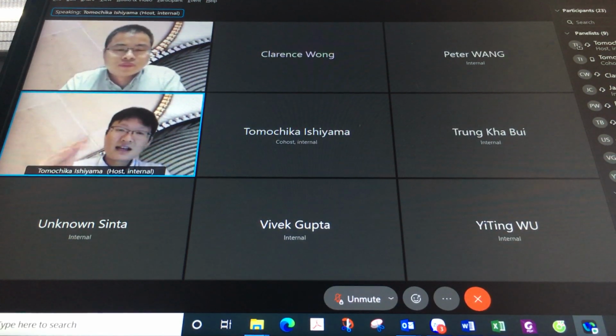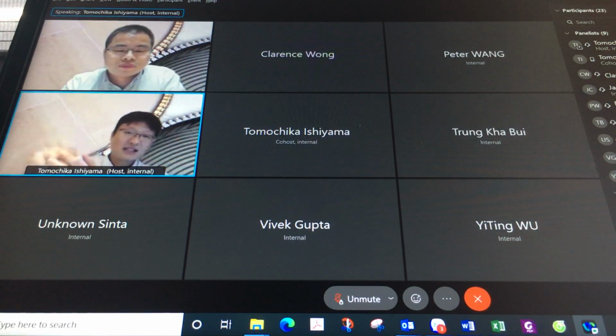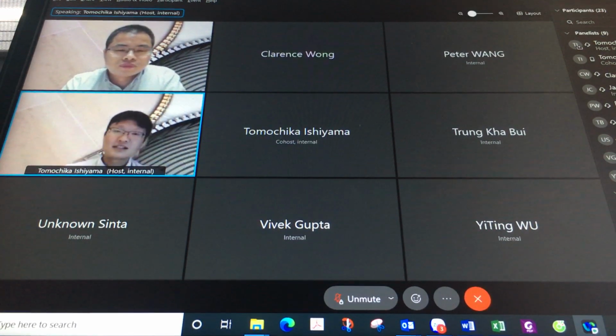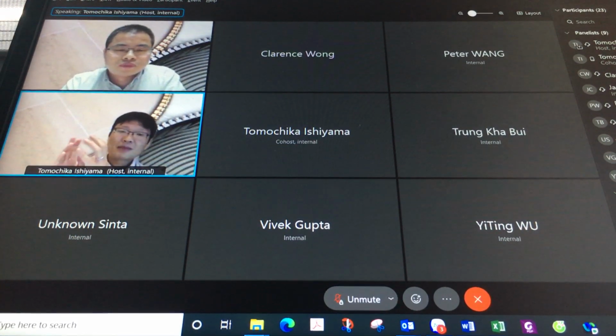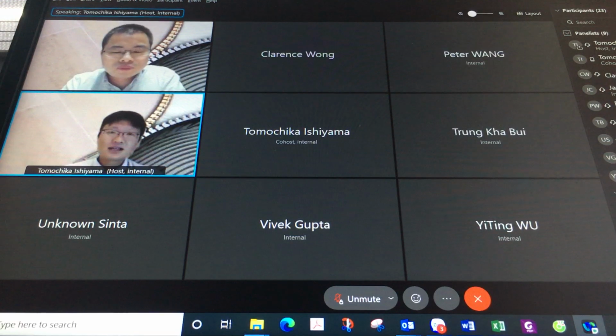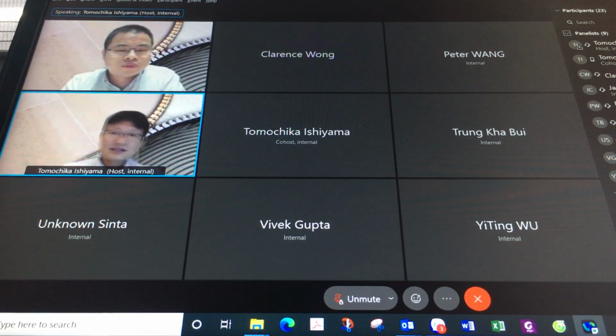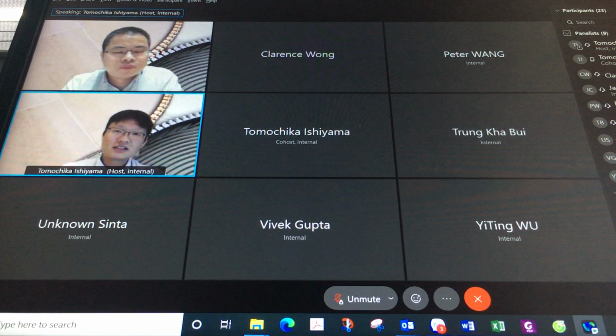When I say tile adhesive, I'm talking about the low-performance CTA, for example, when you just mix cement and sand and a little bit of some additives, or you have this low-performance CTA in the market, where it doesn't really pass the 0.5 megapascal, for example. So these are the areas where we enhance the adhesion from the original adhesion, where it is a critical failure point.